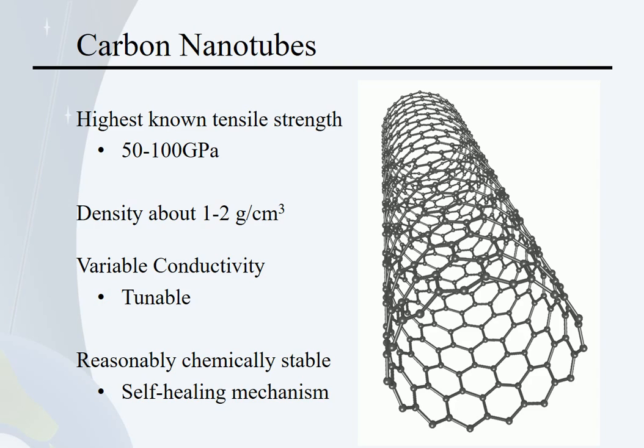Varies a little bit depending on the diameter of the tube and the number of walls it has, but 50 GPa. That's 20 times stronger than the best steels, so pretty good. Density is on the order of 1 to 2 grams per cubic centimeter. Again, that's about the density of water or twice the density of water. About 1/5 to 1/10 the density of most metals. So great strength to weight combination.